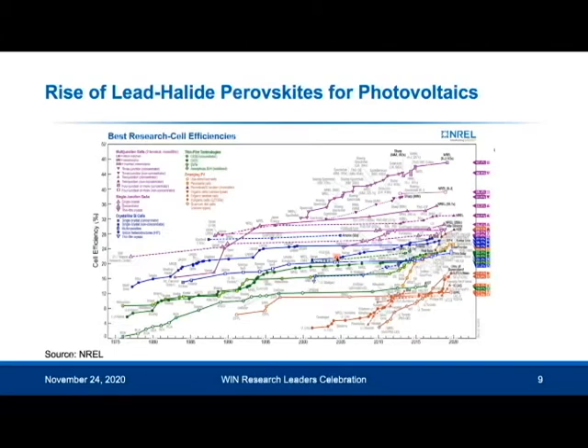So here you see a chart from the US National Renewable Energy Lab that summarizes some of the key photovoltaic technologies. And for the outdoor market, by far the most common material used is crystalline silicon, which is represented by these blue squares here. And you can see that this technology has been developed for well over 4 decades and is now very mature. The efficiencies in the lab have reached 27%, which is very close to the efficiency limit of 29%. There's also a lot of other newer technologies, which are given in this bottom right-hand corner here.